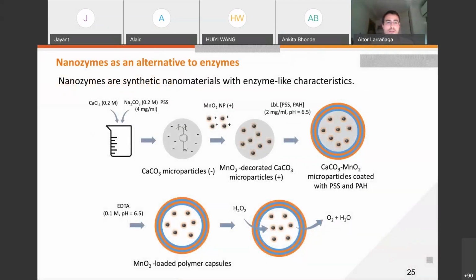Well, as I said, nanozymes are synthetic alternatives to the enzymes. They are defined as synthetic nanomaterials with enzyme-like characteristics. In this case, we decided to work with manganese dioxide nanoparticles. These particles are really interesting because they can simultaneously mimic the activity of catalase and superoxide dismutase, that I would say are the most important antioxidant enzymes that we have in our body.